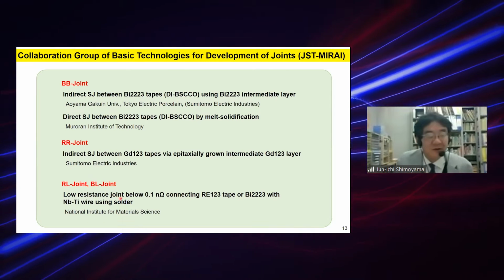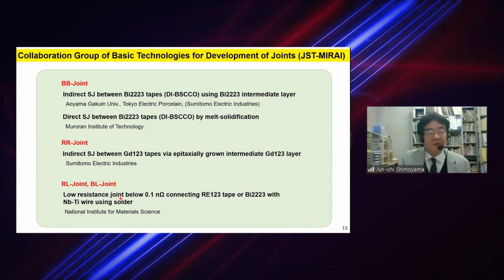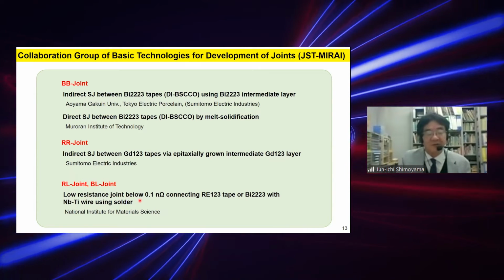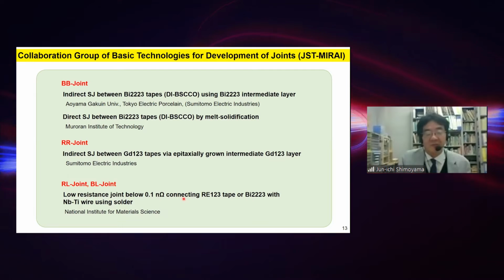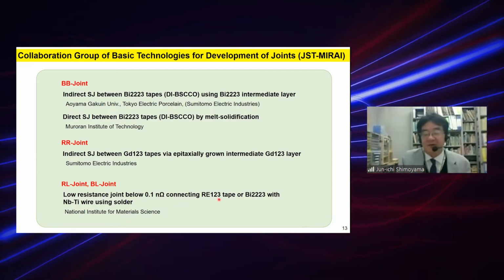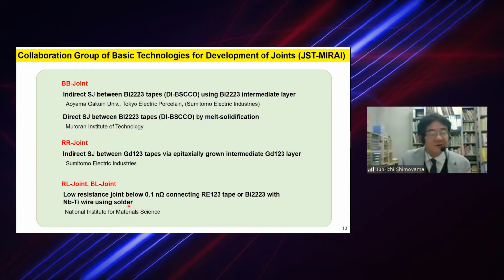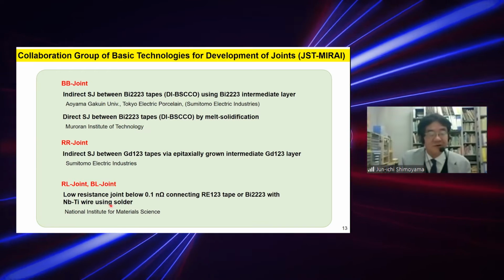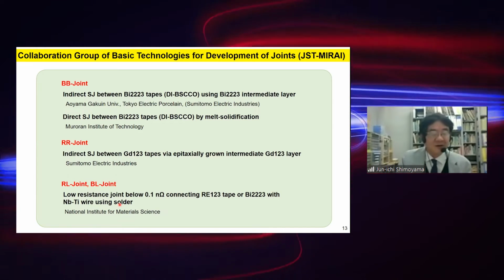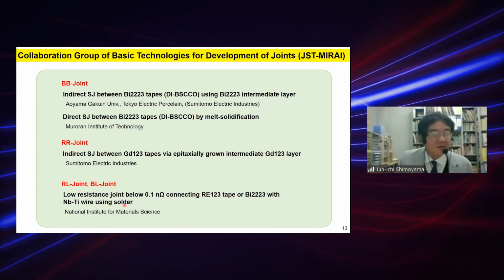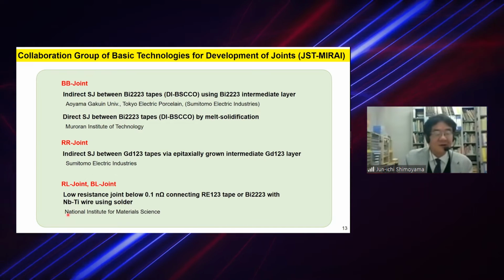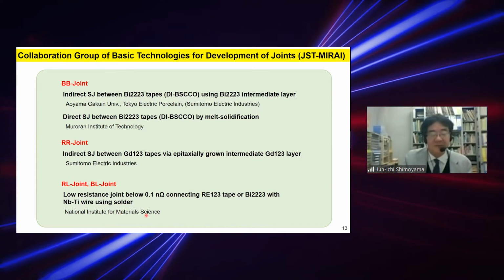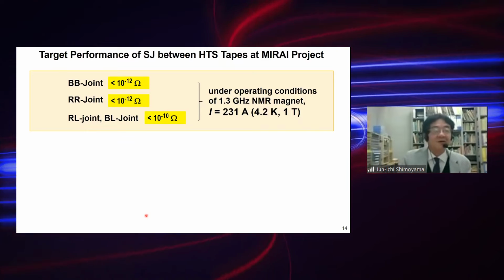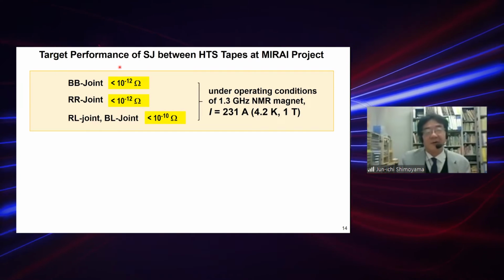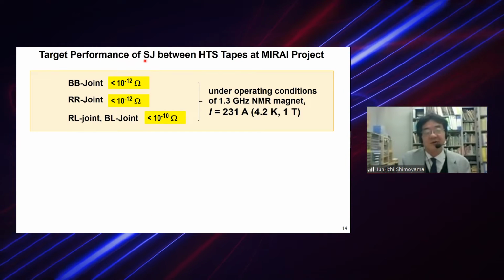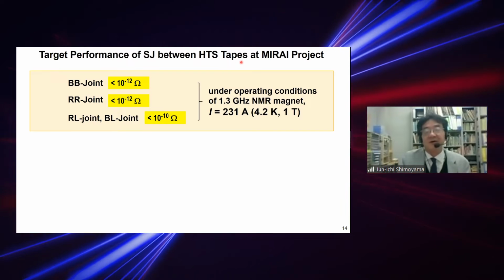In this case, we are trying to develop a very low resistance joint, below 0.1 nano-ohm, connecting RE123 tape or Bi2223 tape with niobium-titanium (Nb-Ti) wire using solder. This study is now conducted by the National Institute for Materials Science, NIMS. So anyway, this is the target performance of the superconducting joint between the HTS tapes at the Mirai project.